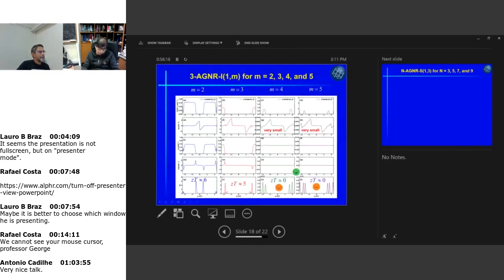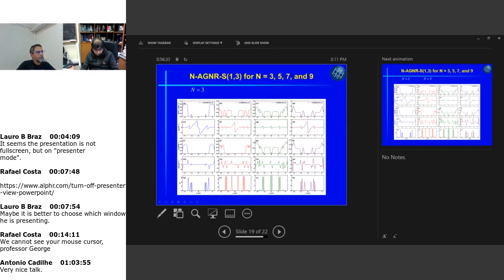So we studied here, the last three slides I showed were for the inline heterostructures. So now we do the same for the staggered heterostructures. So we start by keeping lowercase n equal 1, m equal 3, and we vary capital N from 3 to 9: 3, 5, 7, and 9. Remember that here we have ZT equals 6, so that's okay. And that was the metallic AGNR.